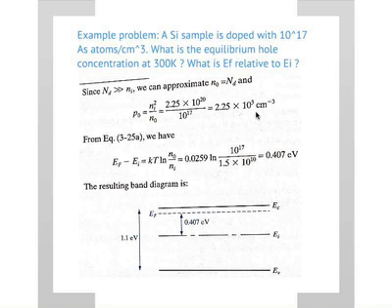Now, look at these numbers carefully. The hole concentration is 10^3 per centimeter cubed. The electron concentration is 10^17 per centimeter cubed. So clearly, there are a lot more electrons than holes, 14 orders of magnitude. Even then, to calculate current, we need to take these holes into account, which is why it's important to calculate. We'll see this next class, maybe next week, at this rate.